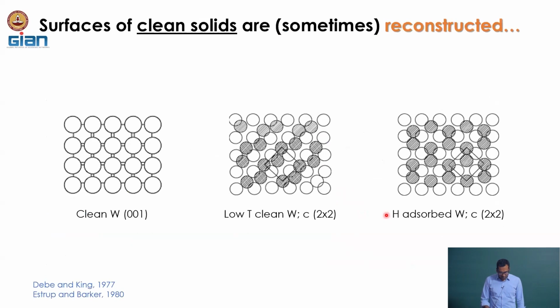Now let us see, do we actually see any change to the surface because of that? Okay. So, on the left hand side, I have a clean tungsten 001 surface, but this is at room temperature. But if I take it to low temperature, now what I find is that the surface layer has a different mesh than the bulk which is present below it. That means temperature is one factor which can affect the nature of the surface, whereas the whole bulk can still be present in the original form. And the other way, without changing the temperature, if we are taking the same tungsten 001, but now we are adsorbing gases at the same temperature, then also because of the presence of these adsorbed gases, we are changing the nature of the surface atom arrangement.